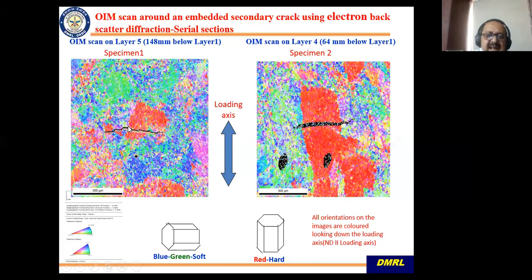What you can see is as soon as the crack goes into a soft region, it either meanders or it blunts. You can see this. So what was said earlier is correct, that the deformation happens in the soft region and it unloads onto the hard region, and the cracking initiates in the hard to deform region. And microtexture plays a huge role in this dwell fatigue failure.